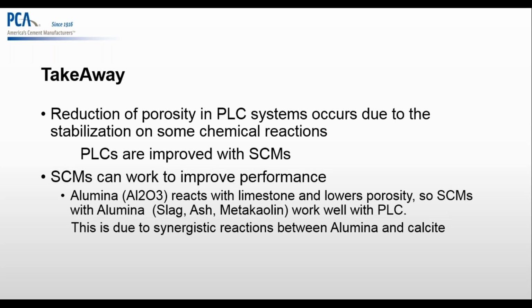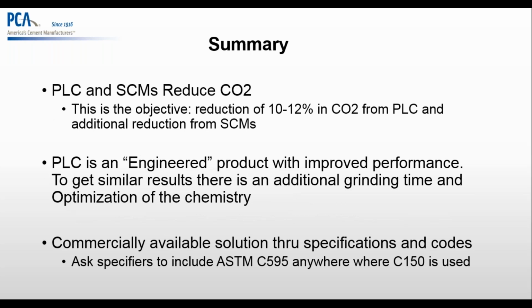beneficial when using PLCs. So in summary, PLCs and SCMs will allow you to reduce the carbon dioxide emissions by reducing the amount of cement, by reducing the amount of clinker in the system. And this will give you a 10 to 12% reduction of carbon dioxide, which doesn't seem like a lot, but because there's so much concrete produced around the world, it can be significant. It can be very, very interesting. And again, by using the SCMs, you can perform even better.